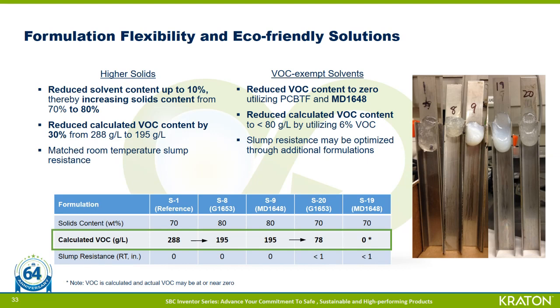So next, we substituted some of the VOC containing solvent for a VOC exempt solvent, but needed to drop the solids content back down to 70%. So again, that was to offset the higher viscosity that was caused by the VOC exempt solvent. However, the effect of the VOC exempt solvent outweighed, in this case, the initial solvent reduction from the calculation.